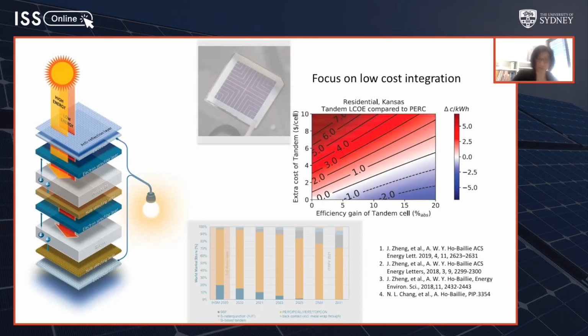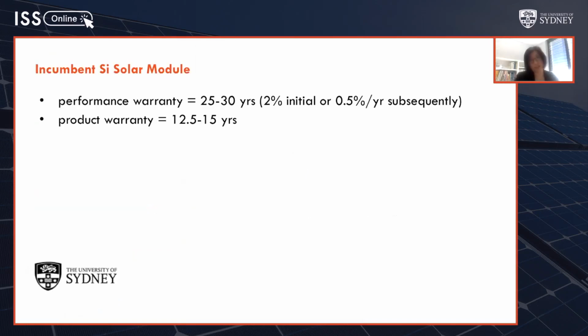The earlier lab cells reported 10 years ago only lasted for a few days. But over the years, the durability of perovskite cells improved. But silicon has a big advantage, as it's stable. So they offer a performance warranty of around 25 years or a product warranty of 12.5 to 15 years. That means if they fail, you should be able to get them replaced. So you can see perovskite's got big shoes to fill.